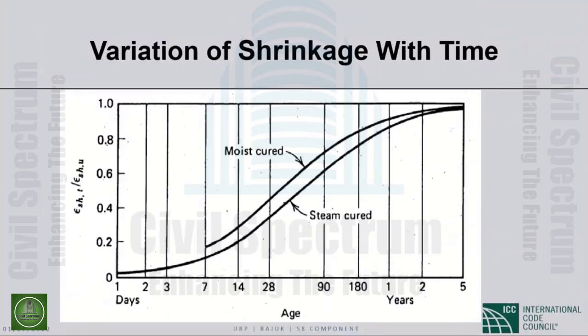Again, this graph for shrinkage variation looks very similar to the creep graph. So again, this is a logarithmic scale up to 5 years. This is the ratio of actual shrinkage strain versus ultimate shrinkage. There's a difference now because it has been shown that moist cured concrete shrinks more than steam cured. I mentioned steam curing before. It may be difficult unless you have the setup to do this, especially in cast in place situations. But in precasting, most yards in the USA are equipped with this because of the time savings, the labor savings and the cost savings. This is another benefit of steam curing. You can see that the shrinkage will be quite a bit less, which probably levels off with time.